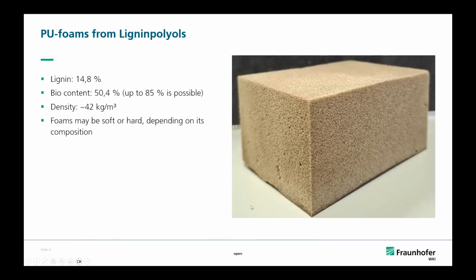So we have a polyurethane foam from lignin polyols, which we made. The lignin content is nearly 15%. This is only an example, so it's plus minus. The bio content for the moment is around 50%, but we are working now to go up to 85%. This is possible because we're using now a biosourced isocyanate as a second component. Density in this example is 42 kilogram per cubic meter, so it's a very light foam, but we can go down to 30. And by modifying the chemistry, we can make very soft foams, but also extremely hard. That is maybe important for a different kind of application, and we can really control this.